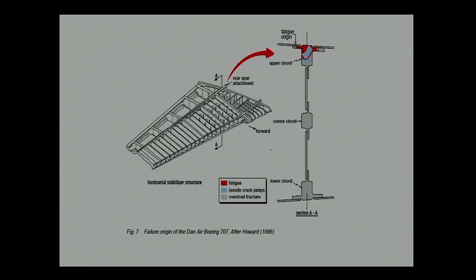So this is in the report, which shows there are 3 stages of fracture or crack propagation. The red mark is the fatigue side, and then at some point the crack has a static jump. That's most likely when you have an overload or a large load, the crack propagated, but then it stopped because of some mechanism that actually arrested the crack. And then you continue with some fatigue loading, and then eventually it broke. So that's basically the story of that part.